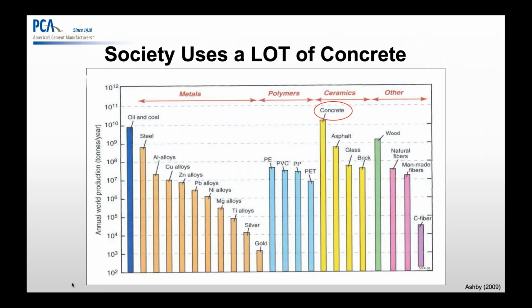More concrete is used annually than any other man-made material by a factor of about 10. Concrete is the most consumed material on Earth, second only to water. Thus, it is important to look for improvements in concrete sustainability. Something like 50% of all man-made materials are concrete by mass, and therefore accounting for 5 to 7% of the world's CO2 production is really efficient. The corollary of this is that anything we replace with concrete will likely drive up overall emissions and energy usage, even if we had the volume of materials to replace concrete, which we don't.